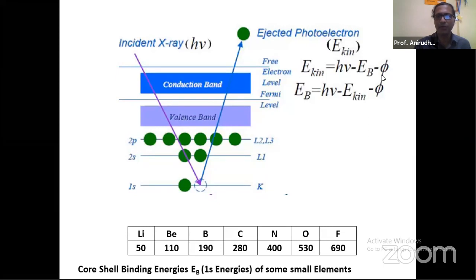But the point to be noted is that the kinetic energy of the electron so ejected will be basically the difference between the energy it has received in the form of this X-ray, and the magnitude of that is equal to h nu. Out of this h nu, a portion EB, which is the binding energy, has got spent in detaching it from there. So that is EB. And then there is a small correction constant, which is a calibration parameter, which is minus phi.